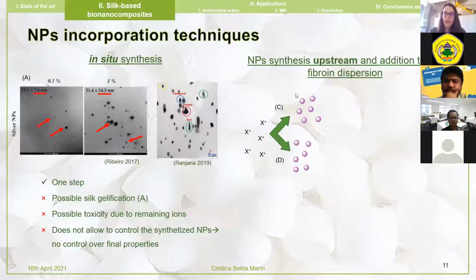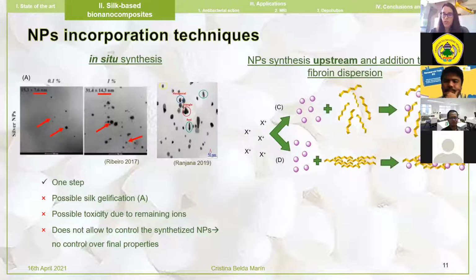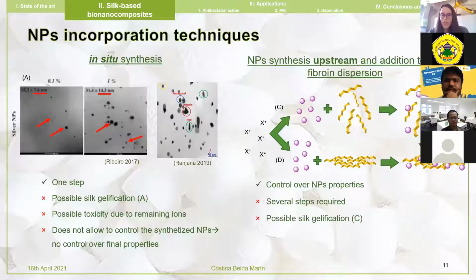So the second technique presented here is the synthesis upstream of the nanoparticles, and then the addition either into the silk dispersion or into the silk material. This step allows control over nanoparticle properties because we have control over the size and shape by synthesizing them before. However, several steps are required. We still have a possible gelification when adding metal nanoparticles into silk dispersion. And if we add metal nanoparticles over the already prepared materials, a release of these nanoparticles could be possible.